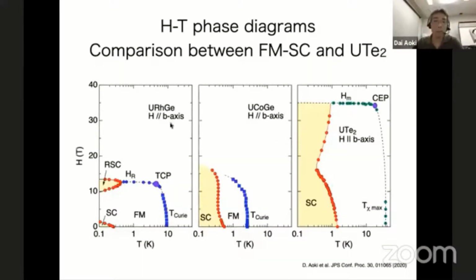Okay, so as a kind of summary, I want to compare with ferromagnetic superconductors. You can see uranium rhodium germanium and uranium cobalt germanium show the reentrant superconductivity or field reinforced superconductivity like this. And uranium ditelluride also shows field reinforced, field reentrant superconductivity like this. But the different point is that in ferromagnetic superconductors there is a T Curie, and the collapse of T Curie induces the reentrant superconductivity like this.